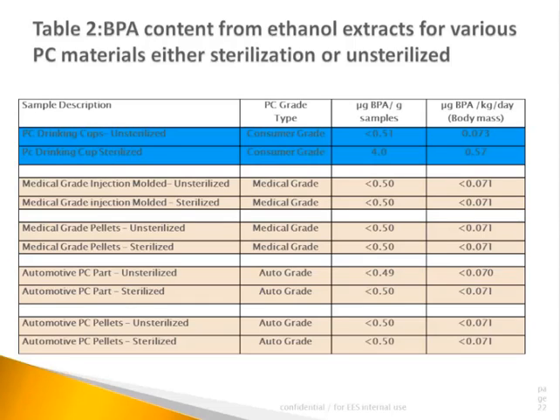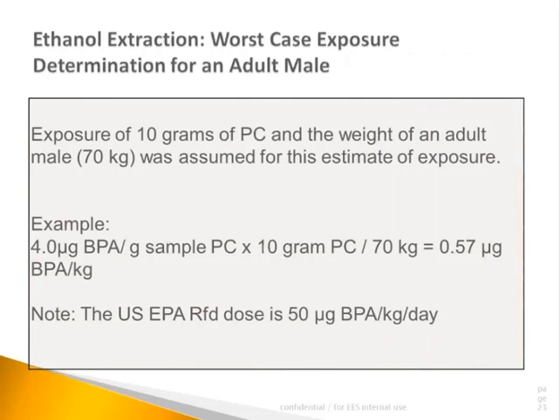Additionally, when it came to the ethanol extraction via HPLC, the trend was very similar to the results described previously, in that, with the exception of the sterilized drinking cup, the BPA concentrations were well below level of detection. The reported values were less than 0.5 microgram per gram polycarbonate. However, the exact concentration of the BPA found in the sterilized drinking cup was 4.0 microgram BPA per gram sample. This value could be converted or normalized to the same unit described by the EPA on the next slide.